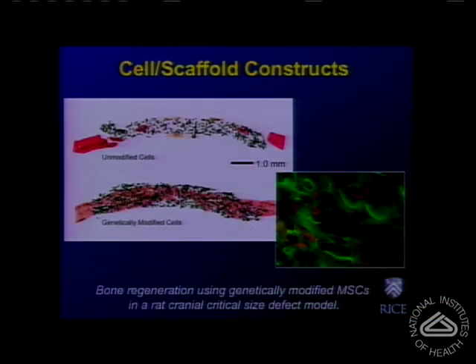Also with those studies, we were able to follow the kinetics of bone formation. Bone formation can originate from the cells themselves that were transplanted. However, what we found was that these genetically engineered cells will secrete factors, including BMP2, that can have an effect on the migration and differentiation of progenitor cells from the underlying dura. So there is a lot of activity now in marrying the advances in tissue engineering with those in genetic engineering using genetically engineered cells.